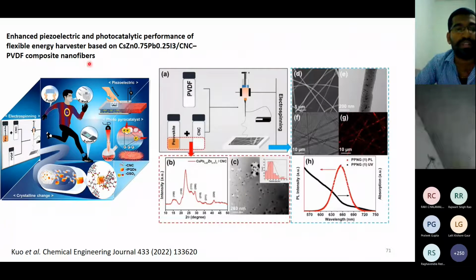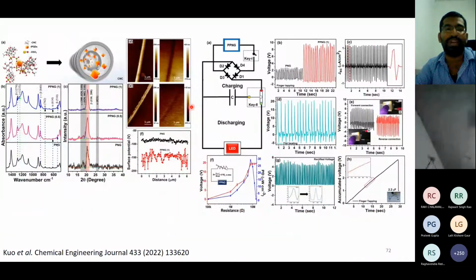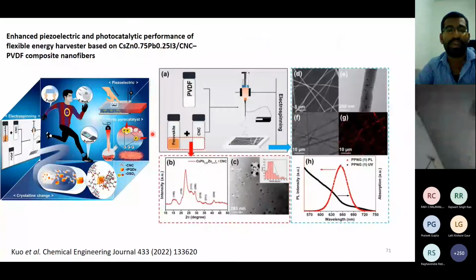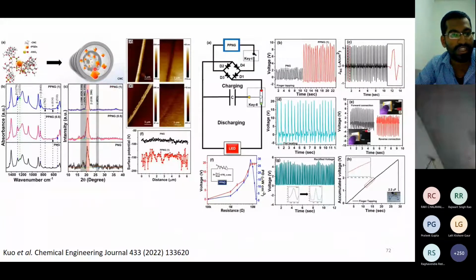In the same way, we are also doing some piezoelectric generation, and here we are using perovskites with the conventional PVDF piezoelectric polymer, because we know that piezoelectric polymers have different phases, and it is quite important to have the beta phase, which has very good ferroelectric property. So we can tune that phase by using fillers, like here we are using perovskite quantum dots. Here you can see this one is your quantum dot, and we have some CNC to give stability, because in the beginning I said that perovskite has very limited stability. To improve the stability, we have to tune the structures and use some ligands to protect the QDs. So we do those things, and then we employ them in the nanofibers.